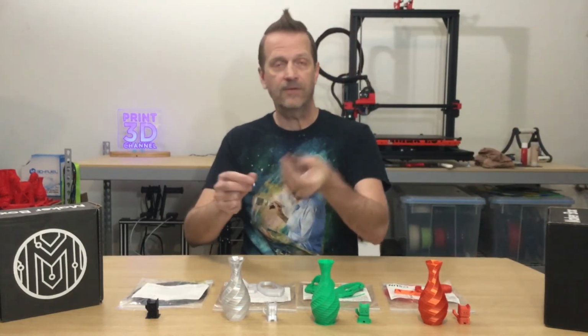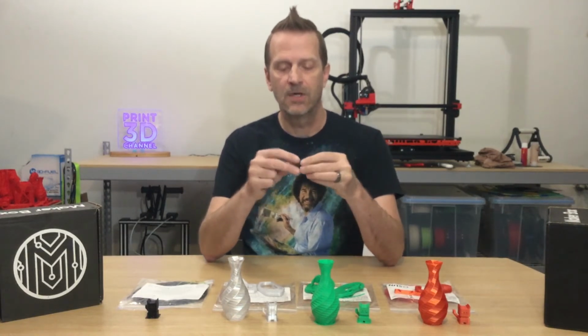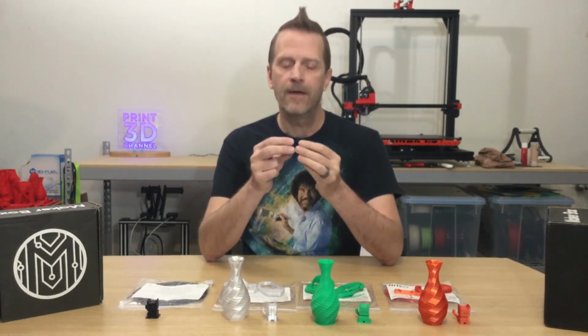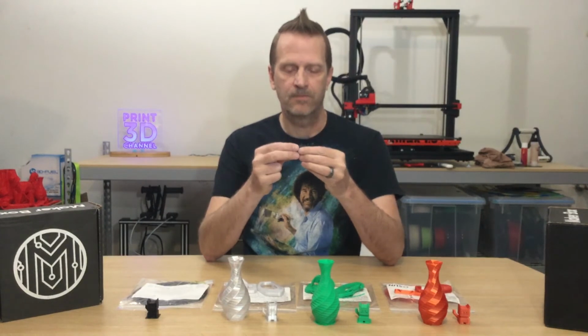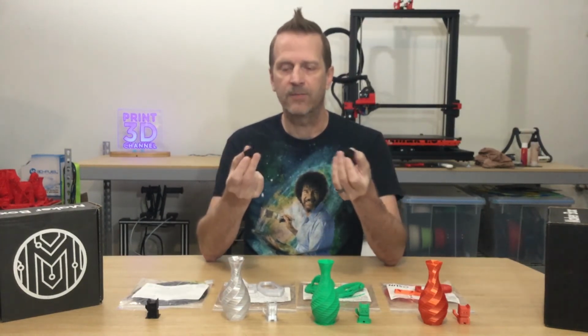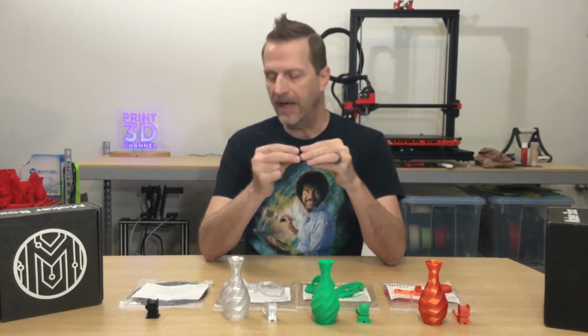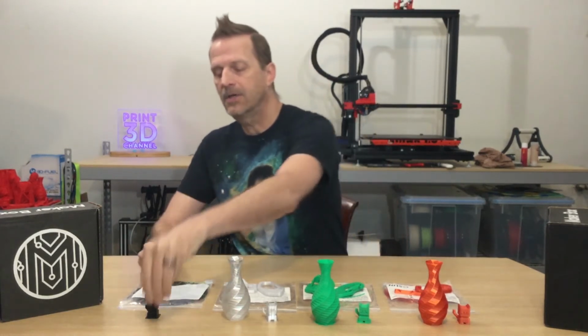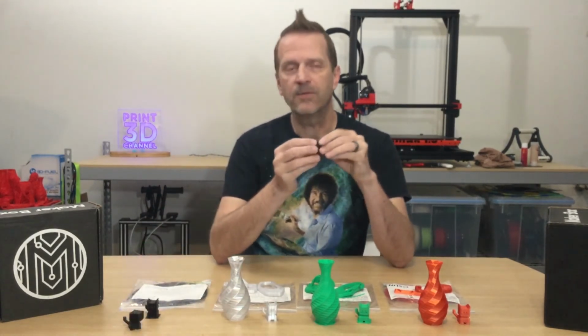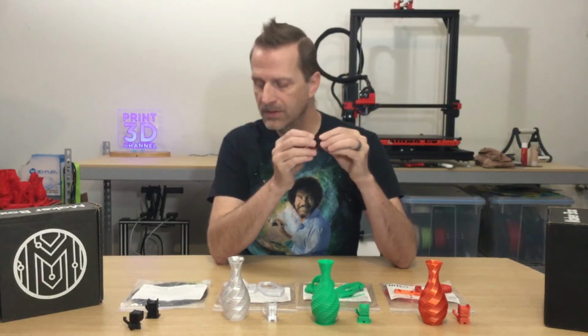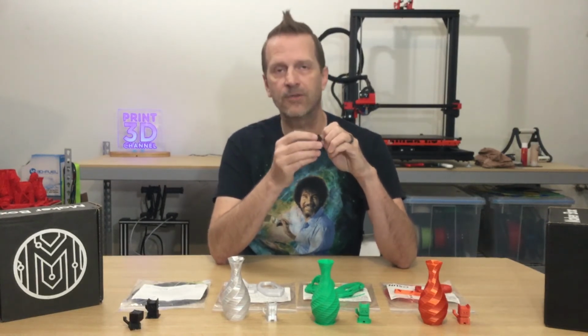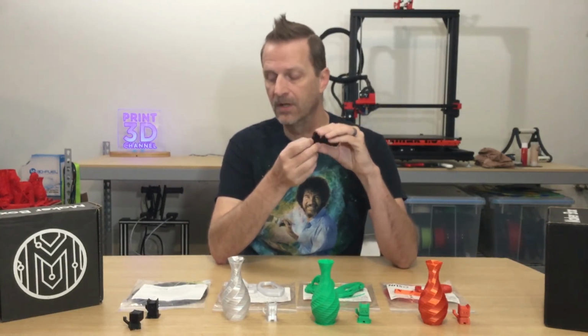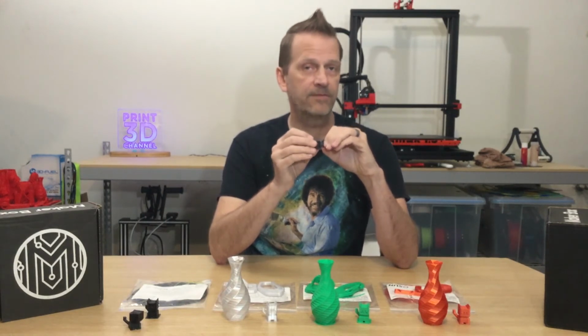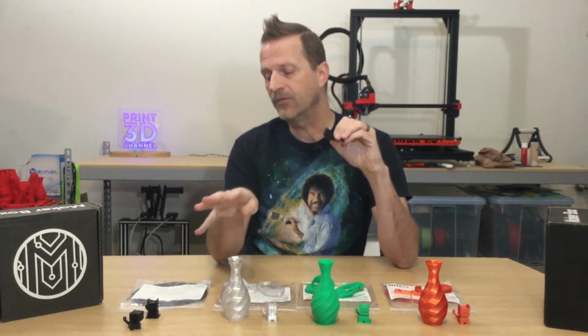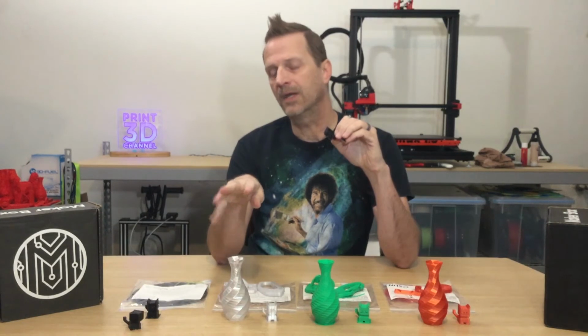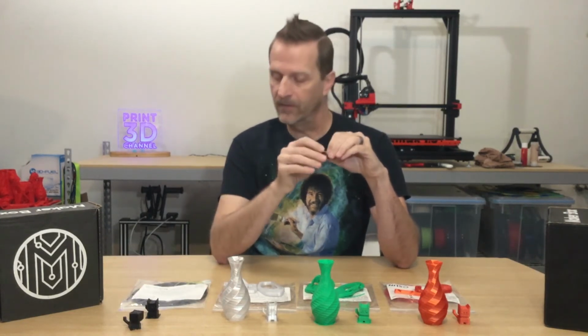So when I took it off, because it just kind of came off, it had already come loose, and I took it off the print head. This came apart like whoop, and there it was. It popped right off. That concerned me right off the bat. So I went ahead and kicked up the temperature to 260, which is 5 degrees over the recommended temperature. Now, I didn't think that would make much of a difference, considering that at 250, it was already warping and the layer adhesion was terrible.